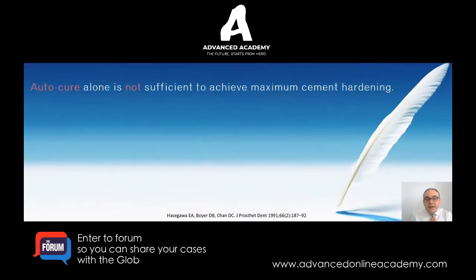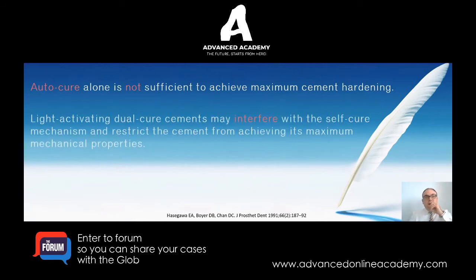If you're relying on the auto cure or the self-cure component of the cement alone, that is not sufficient to achieve maximum cement hardening. There's been a misconception about dual cure cement, saying, well, I used the dual cure cement under this crown, but I didn't subject it to the light curing unit because it has the chemical cure component that will set. Yes, the chemical cure will set, but it won't reach its optimum levels. So you have to combine that with the light cure. It's a combination of two. Therefore, you have to have the chemical cure component and also the light cure component that will maximize the setting of the cement.